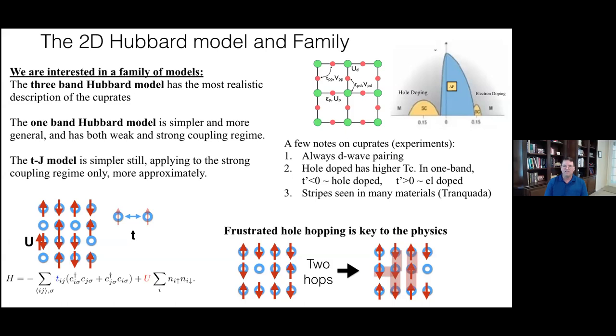And the t prime is always going to be a diagonal hopping. Right? So if t prime is less than zero, that maps roughly to the hole-doped system, so we expect higher Tc, stronger superconductivity, and t prime greater than zero is the electron-doped side.